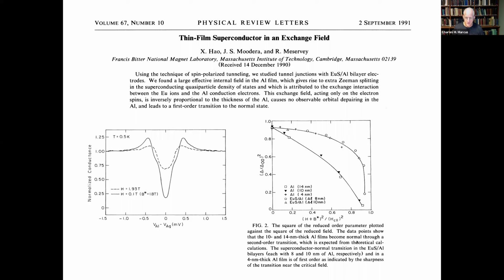The data points show the different films, and what you're supposed to notice is that for the thicker films, the 14 nanometer and 10 nanometer films, as it reads in the caption, the transition is second order, which is expected from a theoretical calculation. The superconductor normal transition in the europium sulfide bilayers with a 4 nanometer thick film of aluminum is first order as indicated by the sharpness of the transition, which means that the gap doesn't really shrink that much as you turn up the external magnetic field, and then it kind of goes bonk. And the data doesn't go exactly bonk, but the first order nature of it is something which matters a fair amount. The first order nature of it is something which has been emphasized in even modern studies.